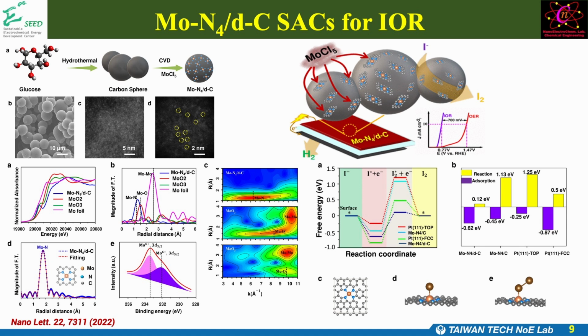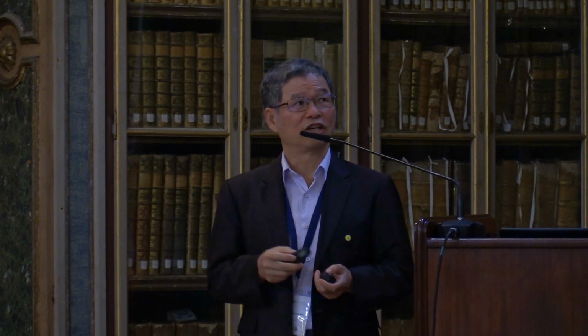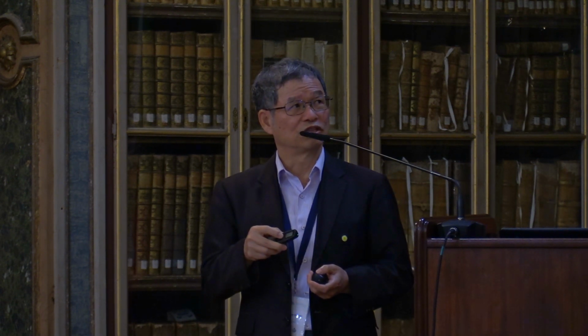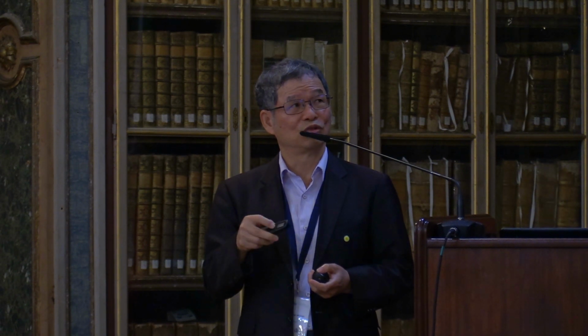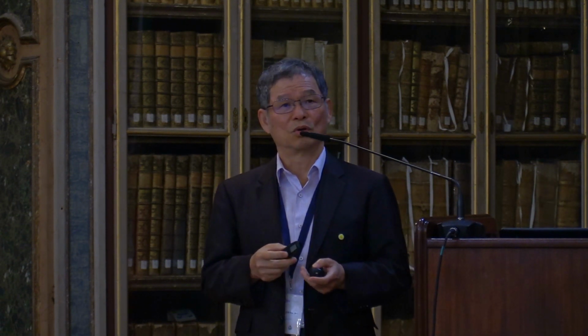Just use glucose to produce the carbon sphere, then use CVD of molybdenum chloride to produce the molybdenum single atom on this defect carbon. We use X-ray absorption and also TEM to confirm this is a single atom catalyst, and also use computation to confirm this defect. Single atom molybdenum can really lower the energy barrier for iodide oxidation. So with this, we can reduce the potential further to around 0.7 volt. So dramatically, we can reduce the energy consumption for hydrogen production.